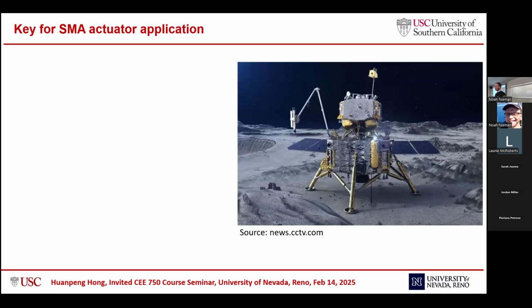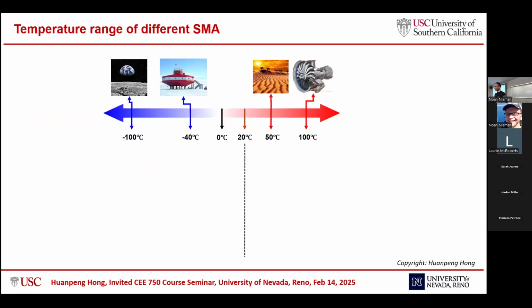The key for the shape memory alloy application includes two parts. The first is the temperature range. The second is the actuation stroke. It's also the strain recovery capacity, or the difference of the deformation this material can generate. So here's a comparison of the temperature range of different shape memory alloys. I divided it into minus 100 Celsius, which is mostly for space extraterrestrial applications, and minus 40 Celsius, maybe for the Arctic or Alaska. 0 Celsius to 20 Celsius, this is maybe for room temperature. 50 Celsius.